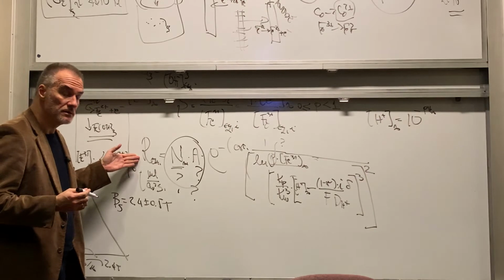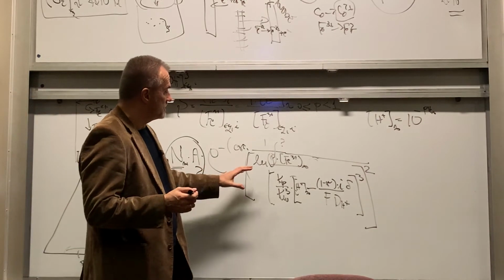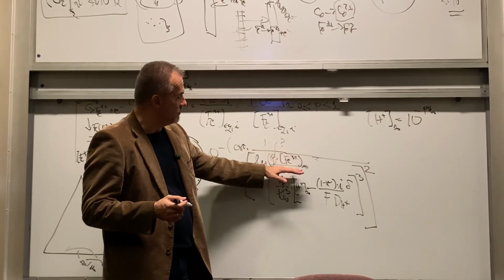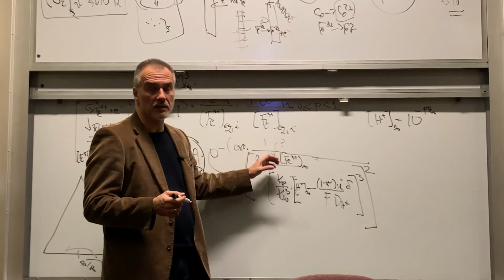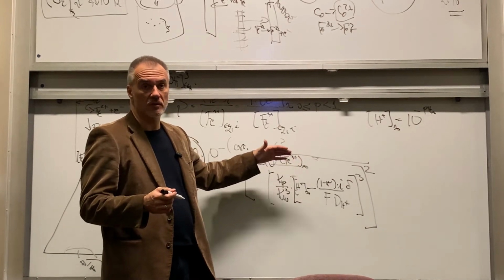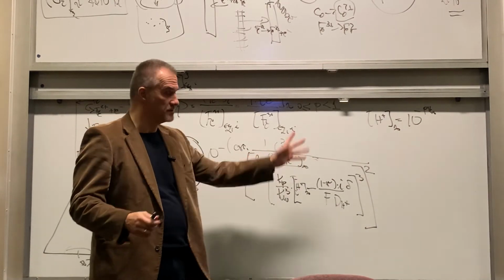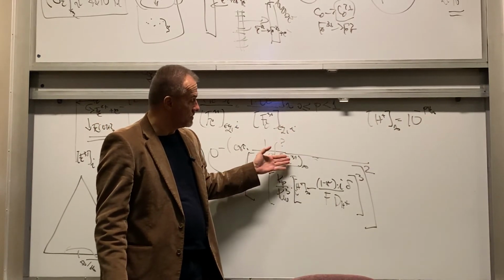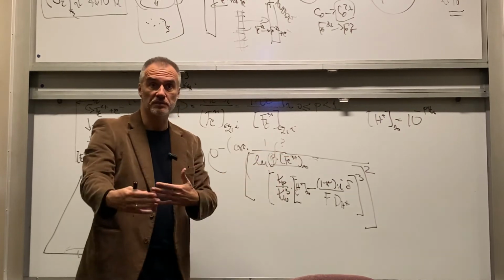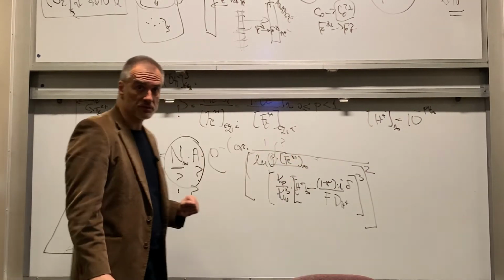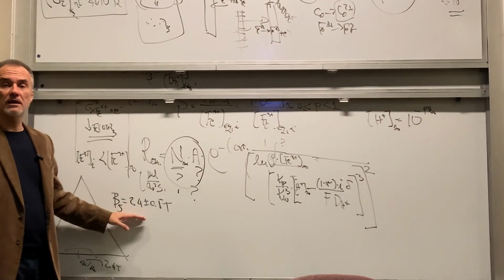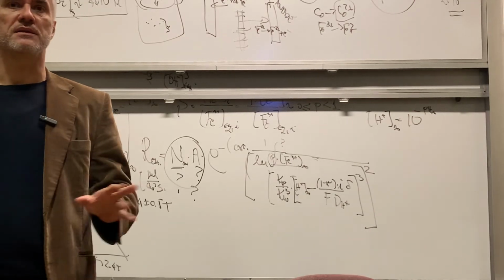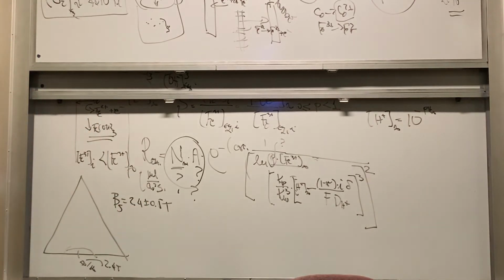if this exists, meaning if this thing here, P times this divided by this, is bigger than 1, because ln of 1 is 0, but ln of less than 1 doesn't have any physical meaning because you don't have precipitation. But if it's bigger than 1, that means this concentration P times this is bigger than this, that means I'm precipitating. So if this happens while I'm doing deposition, I'm going to get an iron hydroxide phase, which is paramagnetic at room temperature. Magnetization is close to 0.